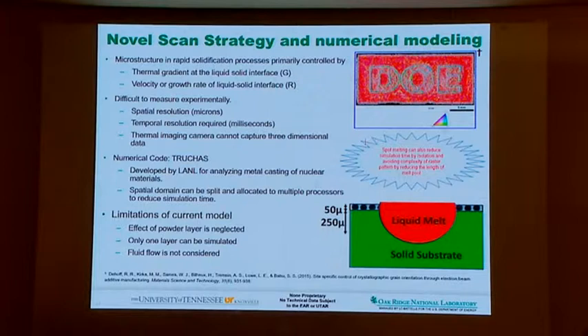So he changed his beam scanning conditions to write DOE, that is Department of Energy. He wanted to make a misoriented growth within the D, within the O, within the E, surrounded by highly textured 001 growth of the FCC. He was successful, but not completely successful, because you can see the red color bleeds over in between these regions too. So he wasn't very perfect. The reason is that it was done by a trial and error method.